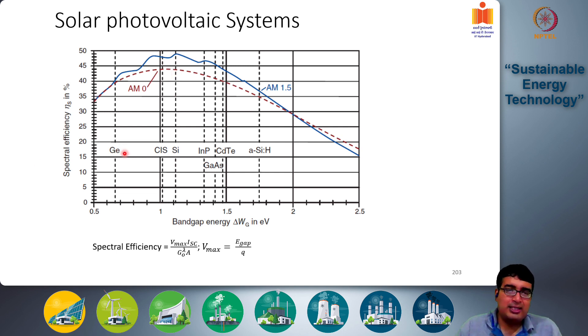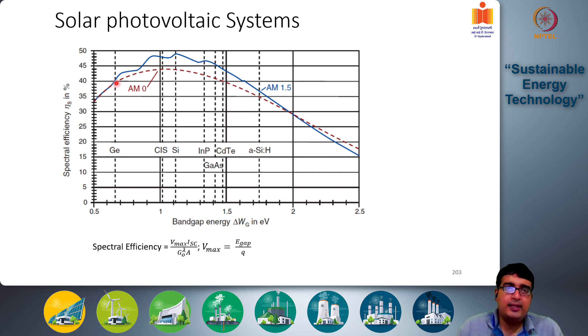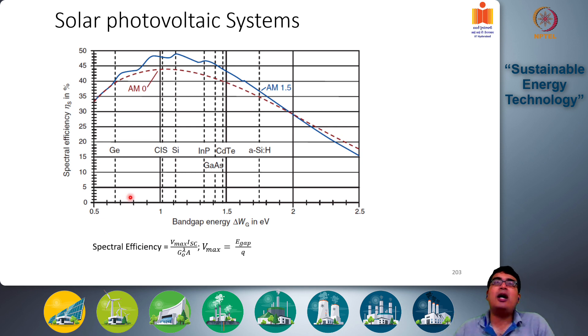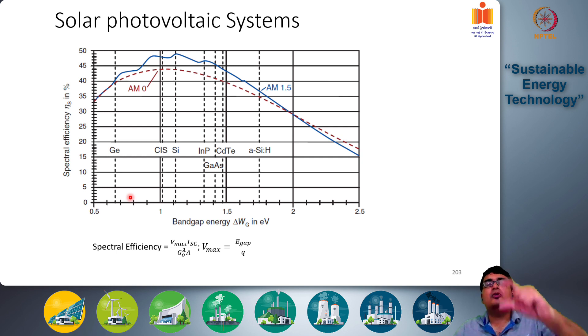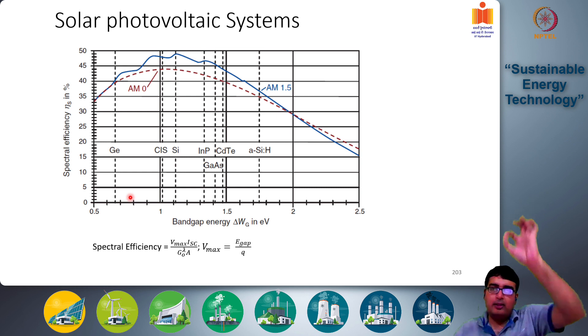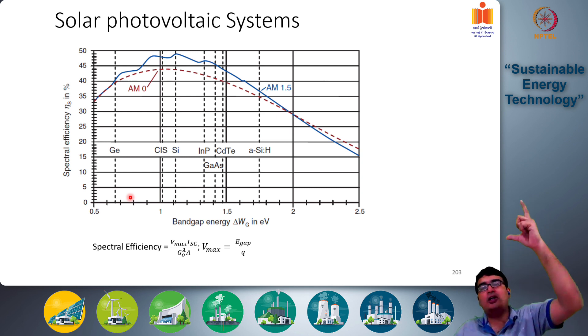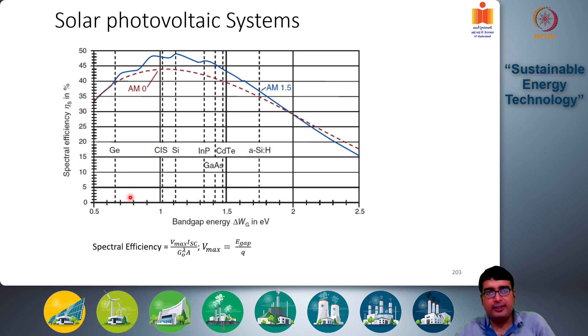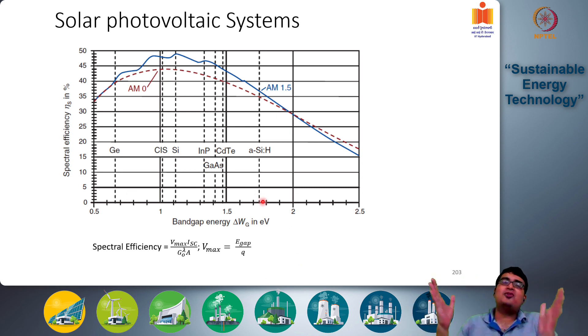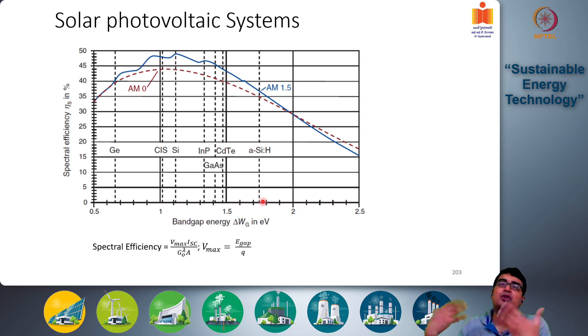There are other solar semiconductors as well. Germanium has a lower efficiency because its band gap is lower. A lower band gap means more thermalizing losses, since electrons can move up relatively easily but a lot of the excess energy in the photons is lost as thermal energy. Whereas very high band gaps lead to transmission losses, because photons will not have sufficient energy to move electrons to the conduction band.